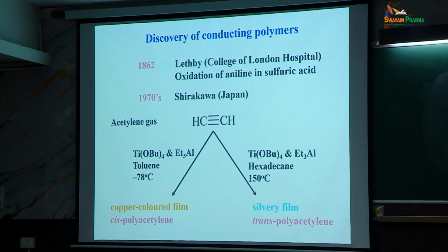This acetylene is a gas, as you know. In oxyacetylene flames, they have the cylinders, oxygen and acetylene. So when you combust them, you get very high energy, so you can fuse metals and so on. So this Japanese group, they had acetylene cylinders. Somewhere it got exposed to some aluminum and some metallic surfaces which can catalyze the polymerization, and they got this copper colored and, depending on the conditions, some silver colored films, which are solid films, from the gas to the solid film. So this was a chance discovery.